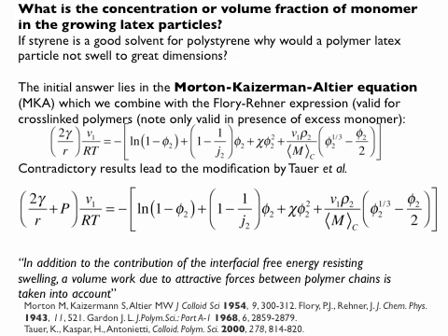Tension times area would be the interfacial energy. So that restricts the maximum swellability. So there will be a finite amount of monomer that could be taken up into a particle. And you could measure that, for example. You could have a bunch of latex particles and expose them to a large excess of monomer, of solvent.